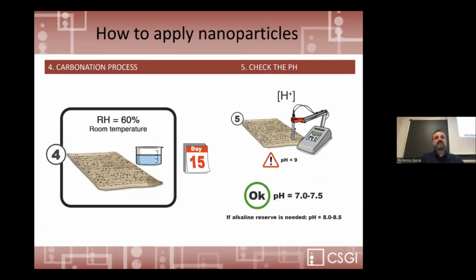Then, at room temperature, with relative humidity at least 60%, we have the carbonation process, which takes, as I told you, a few weeks. And then we check the final pH. The application of nanoparticles allows repeating the process step by step to get the final pH. And this is a completely different approach with respect to other methods where the control of the final pH is